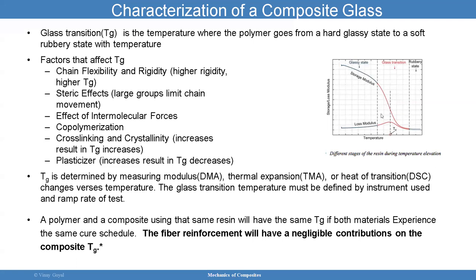A polymer and composite using that same resin. So listen to me very carefully. A polymer and a composite using that same resin will have the same TG. Both materials exhibit the same cure schedule. That's extremely important. Say somebody entered a cure schedule that was incorrect.